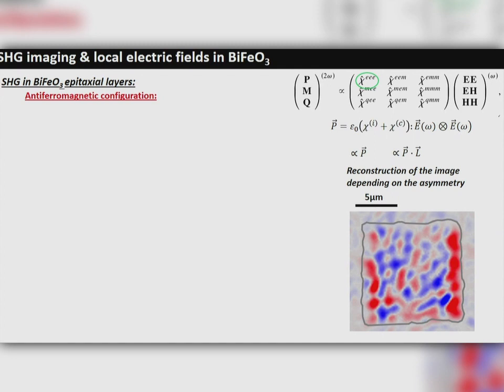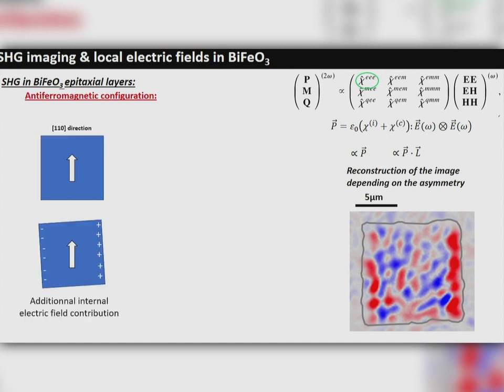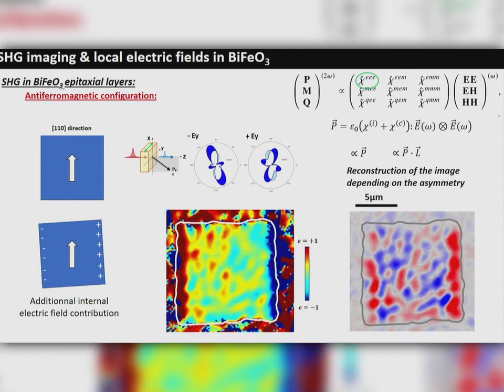And something we wanted to note is, for example, if you look at these edges, it seems that we have lost some kind of long or big red domains, antiferromagnetic domains. And what you have to know is when we have written this with the PFM, we were not fully aligned along the 110 direction. And the ferroelectric polarization will lie anywhere along this 110 direction. It's locked on the crystallographic axis, okay? And by just rotating it a bit, then you create some electrical charging on the sides. And so this is basically a wide field, and you note, as with my little demonstration, that we have this kind of small rotation. And if you, for example, report this small dependence here, you see that on the edges, then it clearly appears that we have this small contribution. Forget about this, because this is only true for the analysis in the single ferroelectric domains. So then you see, for example, with our technique, we can see that we have antiferromagnetic domain, we are able to image them, and we can even see this locking with the electric field.